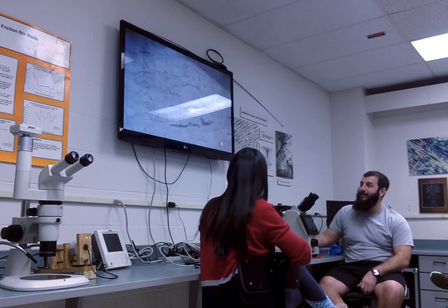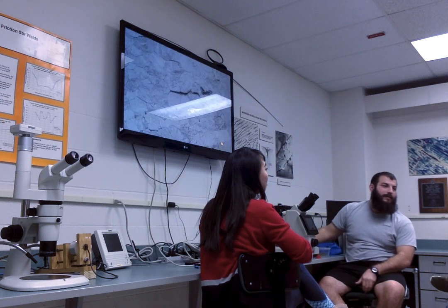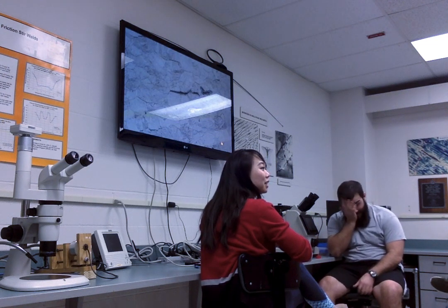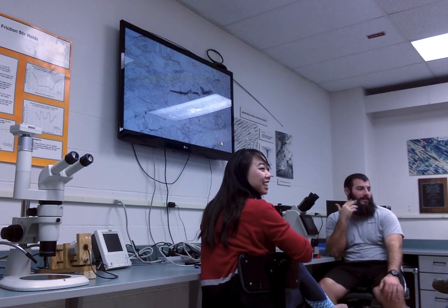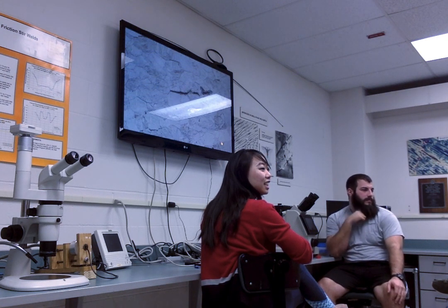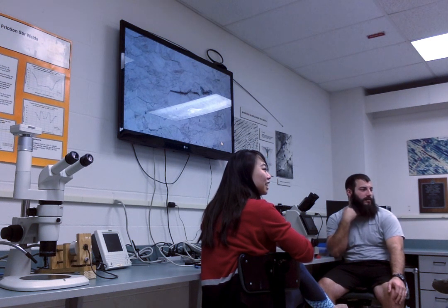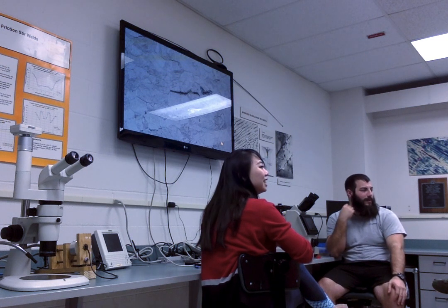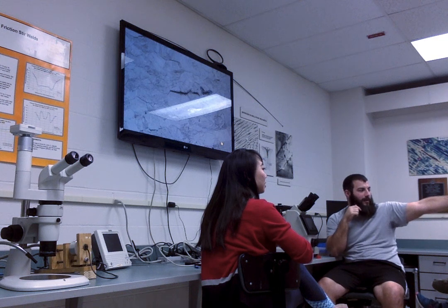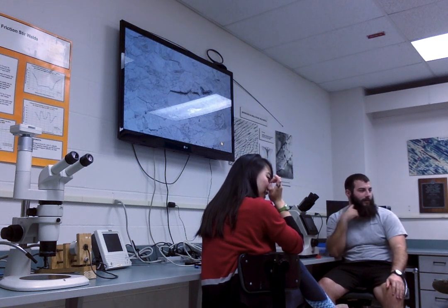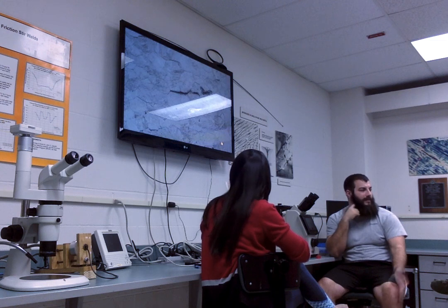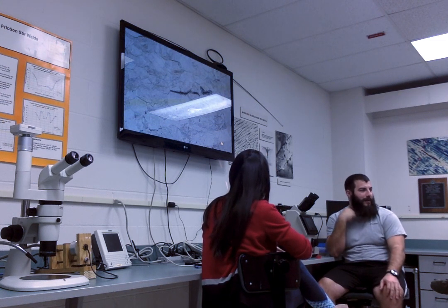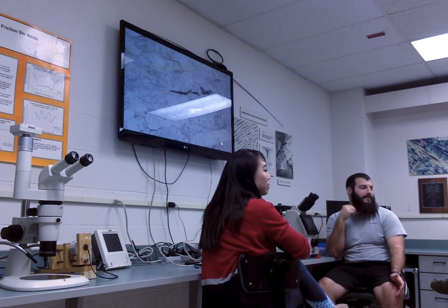So, what's the microstructure here? What does it look like? What are we thinking? Who else? We'll eventually run out of options. Ferrite. Martensite. Austenite. That's wrong. Okay. We're left with one. Tempered martensite. There we go. It was reheated, guys. Come on, that should have been a giveaway. Alright, so tempered martensite. If you reheat something, what are you bound to get? And the precipitates are pretty small, so that's why we can't see them.